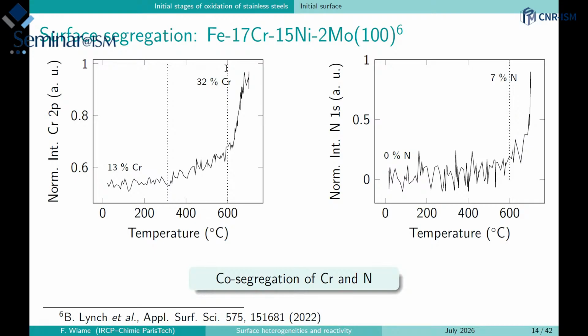We can also see some nitrogen, which is in fact only present under the form of traces in the bulk, but which can be significantly present at the surface due to annealing. And so there is a co-segregation of the chromium and the nitrogen at the surface after 600 degrees Celsius.